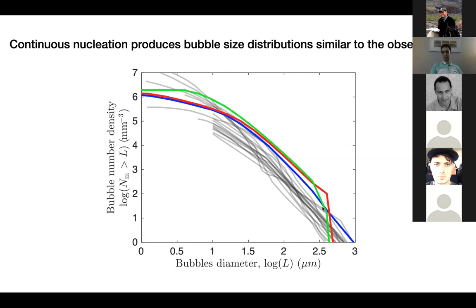For those that are closer to the center, more bubbles nucleate in the reservoir, causing this sharp increase in bubble size distribution. But overall, our model suggests that when nucleation starts from the magma chamber, it results in continuous nucleation throughout magma ascent in the conduit, and that results in a bubble size distribution similar to observations. Thank you.